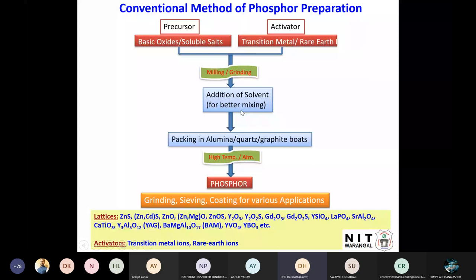Once you mix it, you pack it in alumina pots or graphite boats, and with high temperature treatment in a particular atmosphere you get the phosphor. This is the conventional phosphor preparation technique. Once the phosphor is made, it will be like a piece of stone. Then again, you have to grind it to powder and sieve it to remove bigger chunks. And the final powder, you can use for coating for various applications and so on. So this is the method of preparation of bulk material.